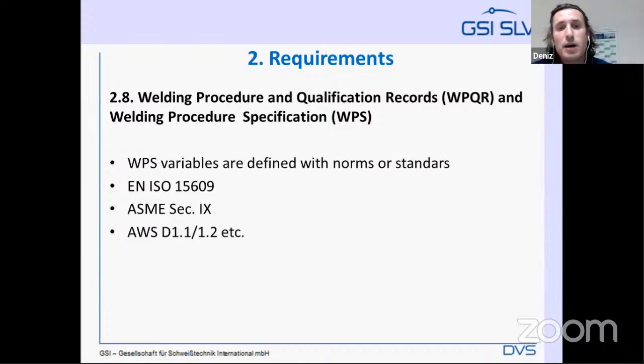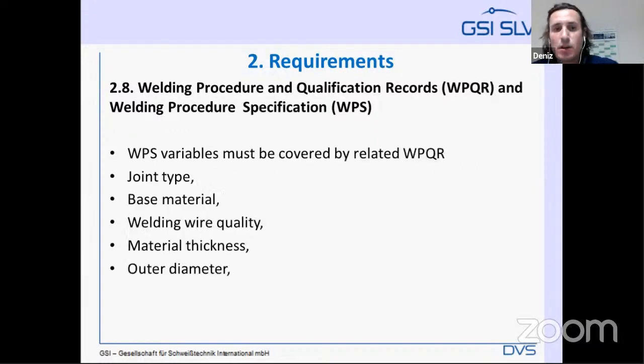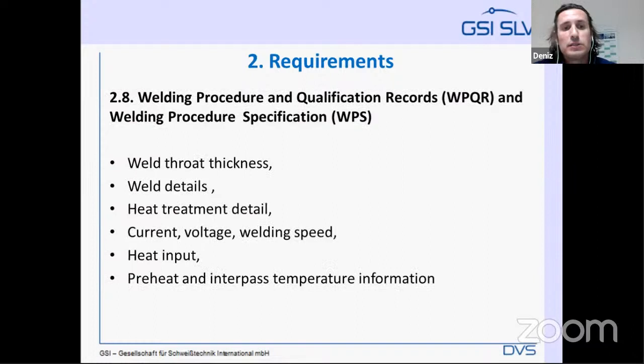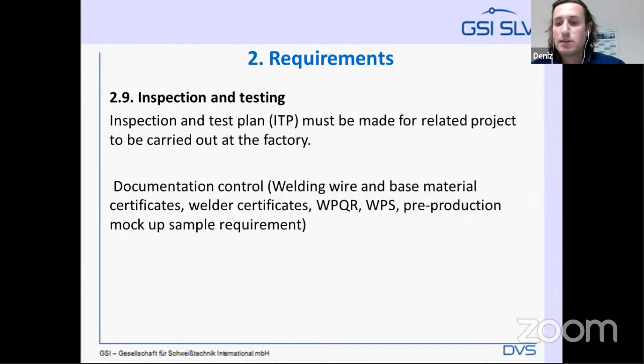And WPS variables are defined with norms and standards. For example, in Turkey, we use ISO 15609, or you can also use ASME Section 9, etc. Variables must be definitely covered by the related WPQR. These variables are joint type, base material, welding wire quality, material thickness, outer diameter, weld throat thickness, weld details, heat treatment detail, current, voltage, welding speed, and heat input, and preheat and interpass temperature information must be given at the WPS.